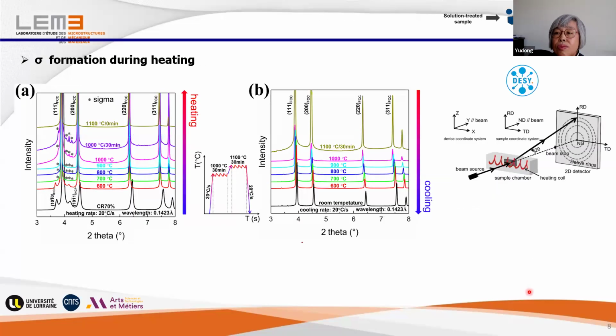After that, we made reheating, or what we call recrystallization. This is under inspection by synchrotron diffraction. At the beginning, the spectra look like this, mainly composed of FCC phase but with a certain amount of HCP phase, which was introduced during rolling. When we increase the temperature with this heat treatment regime, we can see this HCP phase disappears. But when the temperature reaches 900 degrees C, we see additional peaks appearing.